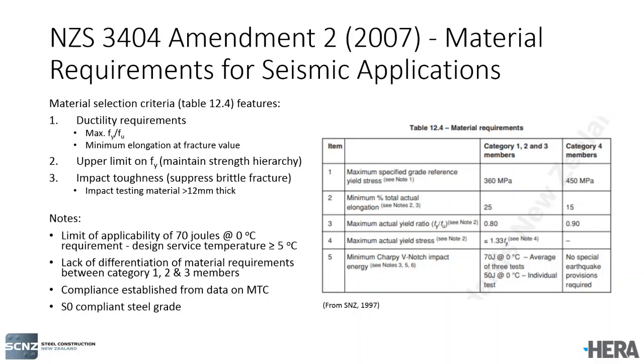The table 12.4 material requirements also include an impact toughness requirement. So this was a 70 joules at 0 degrees requirement that was introduced. This was an average of 3 tests with a minimum of 50 joules at 0 degrees from a single test. There is a limit of application for that 70 joules at 0 requirement. If you look at the notes under table 12.4 in the fine print, it says that the design service temperature must be at least 5 degrees Celsius or greater.